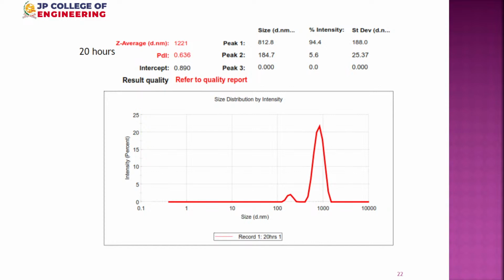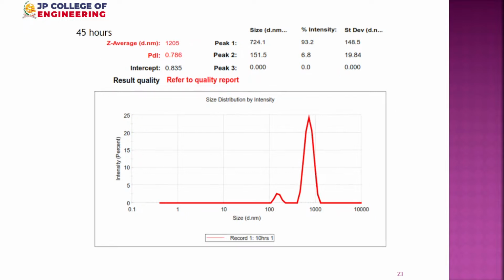Next slide, please. Yeah, okay. So this is 45 hours. We got around 724 nanometer. See the first line, peak one, 724 nanometer. Then when we doubled it to 100 hours, it is not giving much in results. Therefore, the maximum fineness we can achieve is 700 nanometer, 0.7 micron, submicron levels.